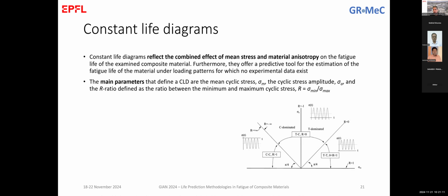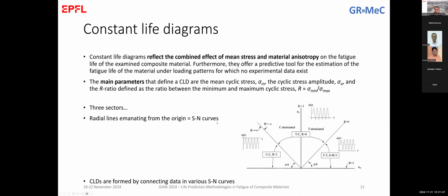The CLDs are defined by the main parameters. We have the mean stress axis. The horizontal axis corresponds to the mean stress of the fatigue loading. The vertical axis is sigma alpha, so the amplitude of the fatigue loading. These radial lines are the SN curves for specific R ratios. And R ratio, you remember, we defined it as the ratio between the minimum over the maximum cyclic stress. And in the diagram, we can see three sectors.